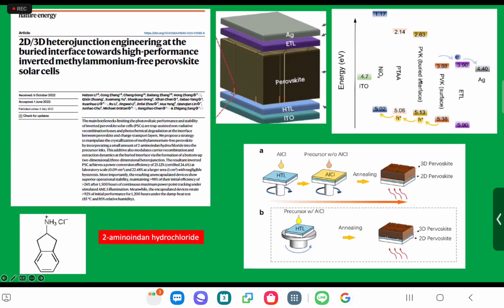Now, the surprising observation is if you just make that perovskite per se as a 2D layer, it doesn't work as well because it produces an electronically blocking interface. Everybody has to ask the question: if I have a 2D perovskite that's coplanar with the support, how does the charge get through that spacer layer? For some fortunate reasons, the self-assembly still lets the holes get through to the hole select contact.